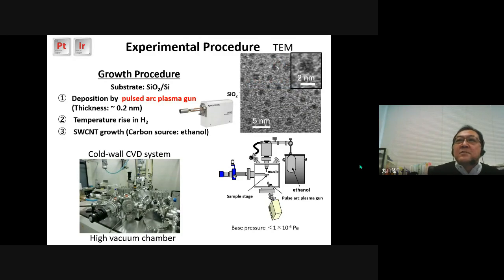This shows TEM image of catalyst particles. The sizes are from 1 to 3 nanometers. To grow single-wall carbon nanotubes, we used a cold-wall type CVD system using ethanol gas as feedstock. This method is called ACCVD, alcohol catalytic CVD.